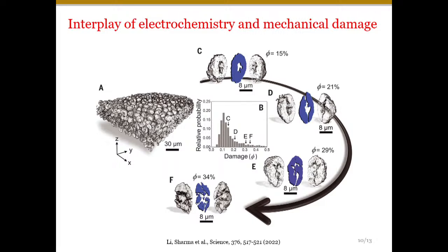Going from this small cyclic behavior to looking at the long term, in collaboration with our collaborators from Stanford, this is a 3D high energy X-ray holotomography image, which gives a lot of detail about particle damage and particle morphology. The resolution is really good, around 20 nanometers.